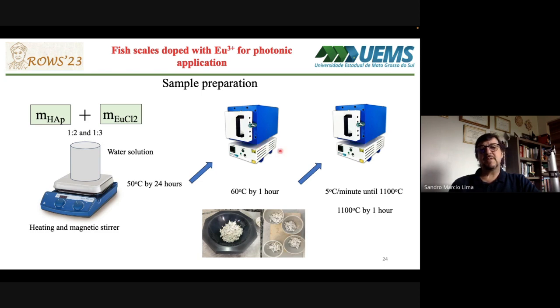After this step, the samples were heated in a ramp of 5 Celsius degrees per minute until 1,100 Celsius degrees, in which it was maintained for 1 hour. Following, the sample was macerated until it turned into a thin powder that was tested as an optical temperature sensor.